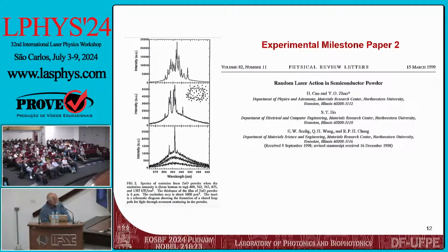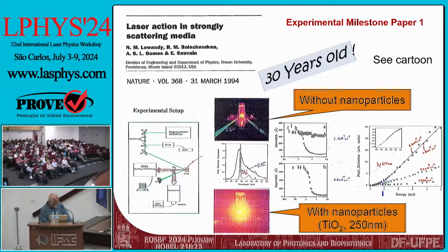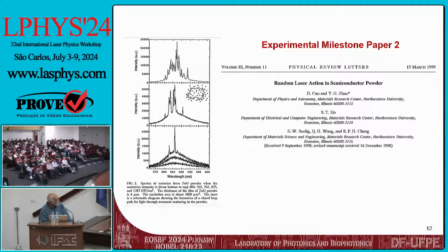So a few years later, 5 years later, Hui Cao and a group used zinc oxide nanoparticles to show that if you have this powder, you could have the same kind of emission. But instead of having a smooth spectrum like we have here for the laser, which we know now that we are in a so-called diffusive regime, she could see clearly those spikes. And those spikes were explained by having this kind of loops.